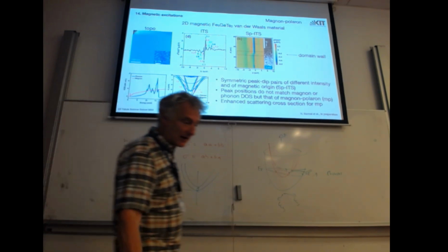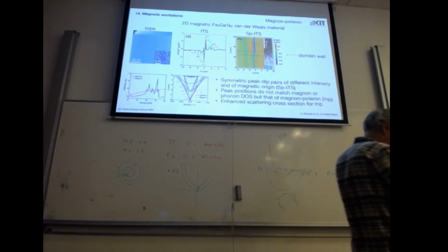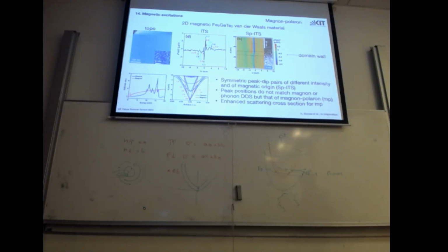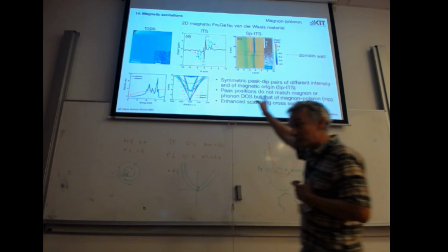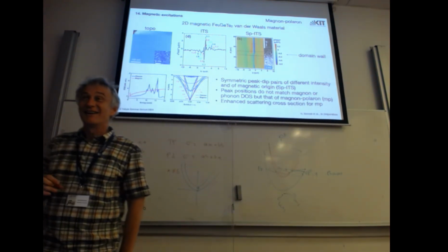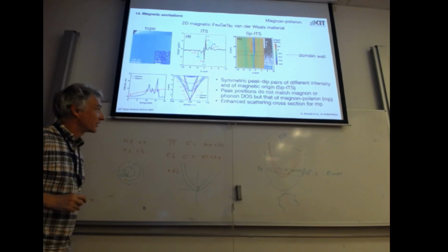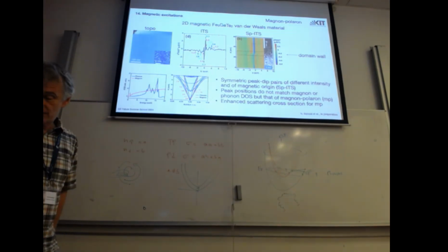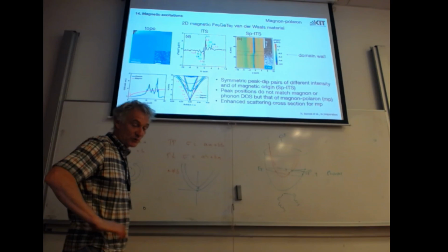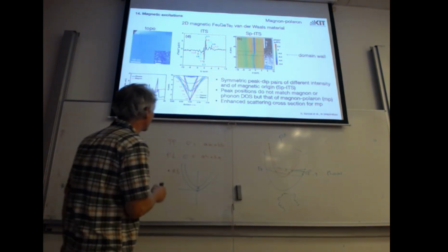And if this is a hybrid object, then you get the matrix element for electron-phonon coupling plus the matrix element for electron-magnon coupling to the square. And you get two new terms which enhance this cross-section. This is what we believe at the moment is the correct answer. So Marcus Gast is doing a calculation at the moment to really prove this, but it's my gut feeling that this will be the answer.